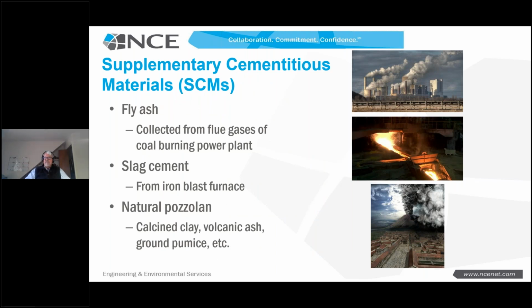Supplementary cementitious materials include fly ash collected from the flue gases of coal burning power plants. Fewer and fewer of these plants are available in the US and elsewhere, obviously because of the switch away from burning coal. We have slag cement as another source, where we can take ground granulated blast furnace slag and grind that up, and it creates an excellent cementitious material. And then natural pozzolans: calcined clays, volcanic ashes, ground pumice, other sources of natural material that are naturally pozzolanic that with some processing can be used. So these are the common ones that have been used.